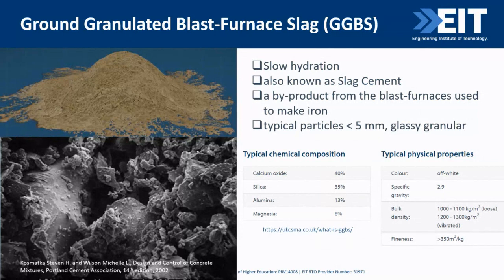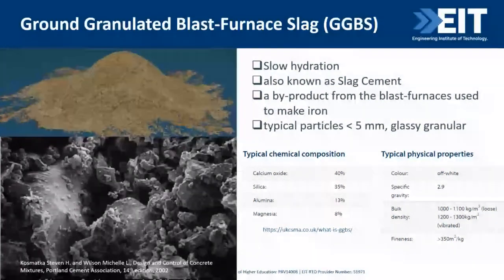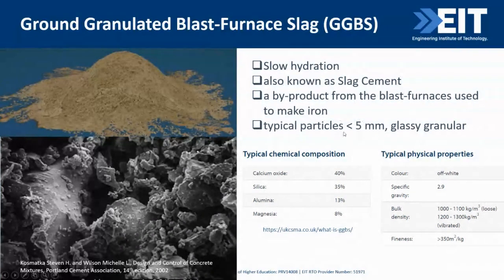GGBS is obtained by rapidly quenching the molten slag by using high pressure water jets in a blast furnace as a byproduct from the production of iron used in steel making. This rapid quenching process transforms the molten slag to a glassy sand-like granulated material with a typical size smaller than 5 mm. These are the typical chemical composition and the physical properties of GGBS. Generally, the oxides of silica, calcium, alumina, magnesium and iron make up more than 95% of the GGBS. And again, we can also see that the GGBS has approximately the same or greater fineness than Portland cement.